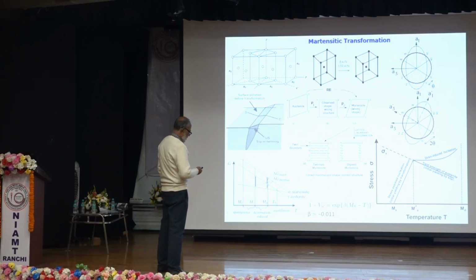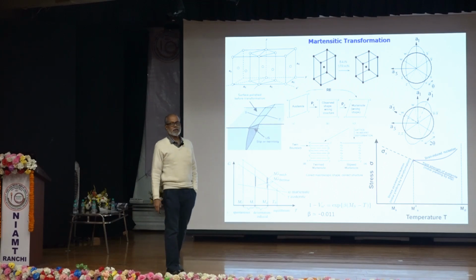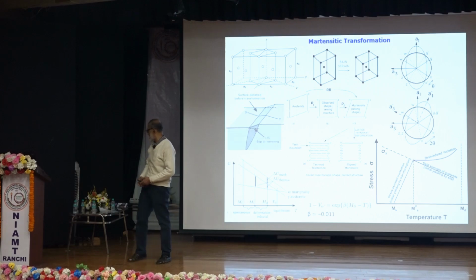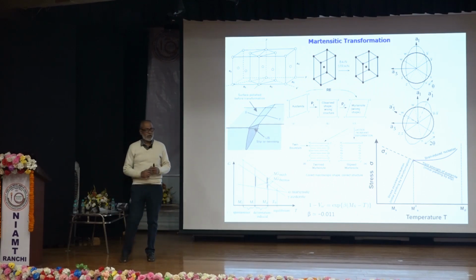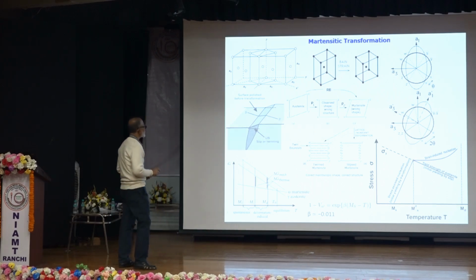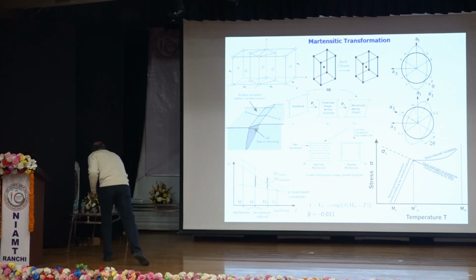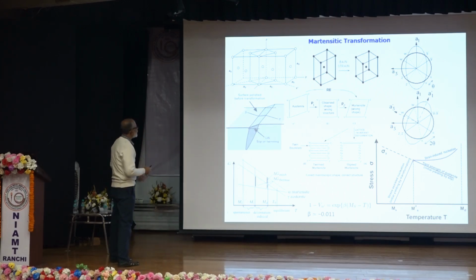Here is an example. This is for steel. Popularly, there are two crystal structures which we use in steel. One is austenite, which is an FCC structure, and the other is ferrite, which is usually a BCC structure. So, Bain had shown, see, this one is austenite. You can see there are atoms at this surface. So, this is a face-centered cubic structure. So, we have considered two austenite cells, okay, two austenite unit cells.